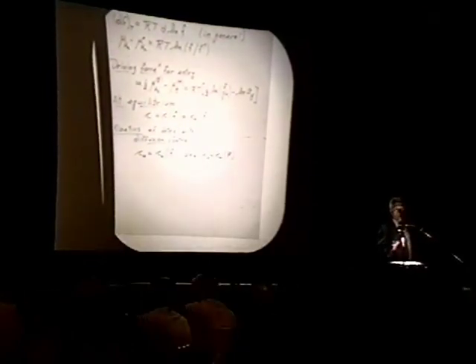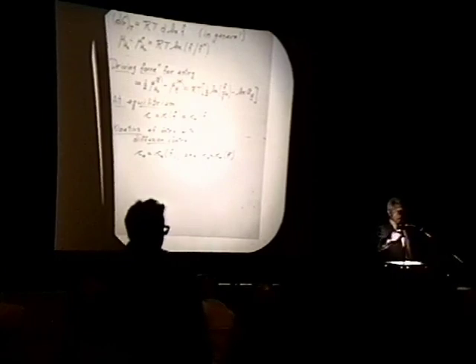And therefore, what I call C0, namely the subsurface concentration just below the input surface of the solid, which controls the subsequent diffusion further into the solid in a non-equilibrium situation, is also a function of fugacity. Now, of course, the kinetics of entry through the interface must be considered in the overall transport process. But if you have diffusion control, not kinetic control, for the ingress between the adsorbed layer and the subsurface layer, then that subsurface concentration is in fact a function of fugacity, and because fugacity is completely determined by the hydrostatic pressure at any one temperature, it's also a function of the external hydrogen gas pressure.